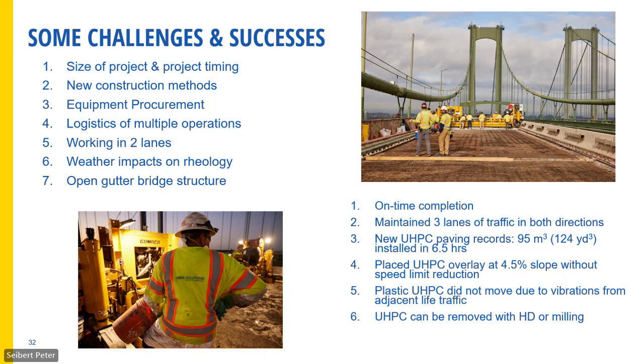Formwork and placing of UHPC, the curing of it. And now that section where the UHPC is cured, you can't pass at all. And the pavers across the bridge. So then on the backside, you have to get it ground, cleaned up. We had to do joint installations at all the expansion and relief joints on the bridge. And just the size of it and the scope of it was a huge logistical challenge.